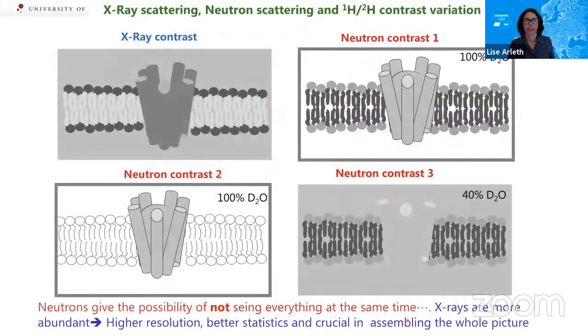So what can we do with X-ray scattering and neutron scattering? With X-rays, when we put a membrane protein in a lipid bilayer, either in a liposome or in a nanodisk, we obtain a contrast that looks more or less like what I've illustrated here. So we have one contrast for the protein, one for the lipid head groups, and one for the hydrophobic tails. And this basically gives rise to a relatively oscillatory scattering pattern, but that is, on the other hand, also very information rich. With the neutrons, we can of course do contrast variation.